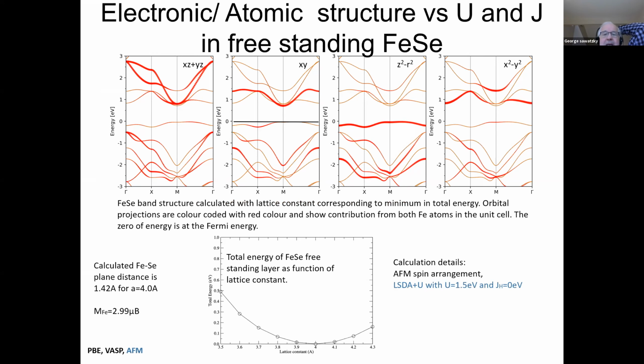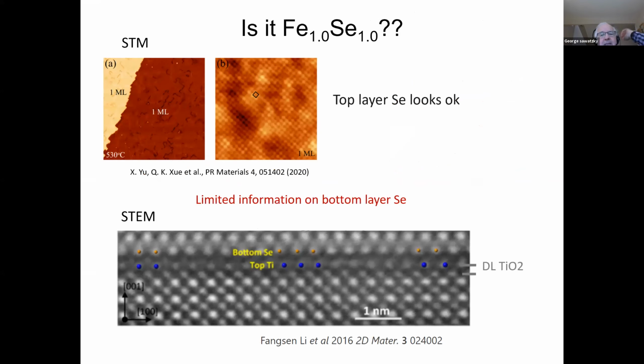Okay, so we then were looking at other things that might happen. For example, the top layer, the top selenium in this STEM data down at the bottom, but also from the very beautiful surface truncation rod experiments that Kazhu did, they showed that the selenium actually is not symmetric. The iron is not symmetric between the two selenium layers. The layer at the bottom is a little bit closer to the iron than the layer at the top, the selenium at the top.